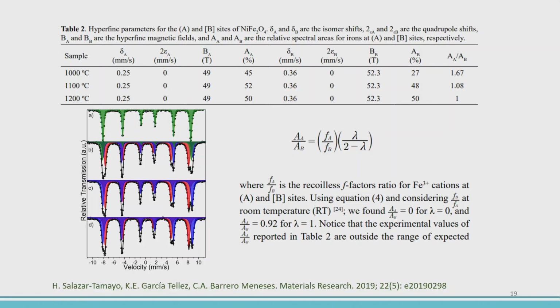And when lambda equals 1, this is 0.92 if we use the value that we published in the previous result. So this is the reverse of the other. That's why it gives the value 0.92. Because this is outside this range, we cannot explain this variation in the area ratio as due to reordering phenomena, because this formula is only due to the cationic distribution of the cations in B. So we have to find another explanation.